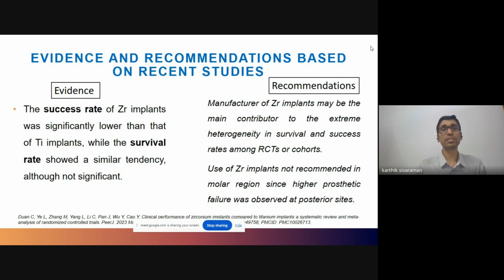Now, when we speak about a success rate over a 5-year period, we expect a greater than 85% for the maxillary implants and a greater than 95% for the mandibular implants. Now, what the authors have stated in this study is that the success rate of zirconia implants are significantly lower than that of titanium implants. The survival rates were also low, but they were not statistically significant. Now, what were the reasons? There were technical complications seen in form of occlusal chipping, and these were attributed to variations in manufacturing methodology. So, according to the authors, the manufacturers may be the main contributor to the extreme heterogeneity in survival and success rates among the randomized clinical trials or cohorts.